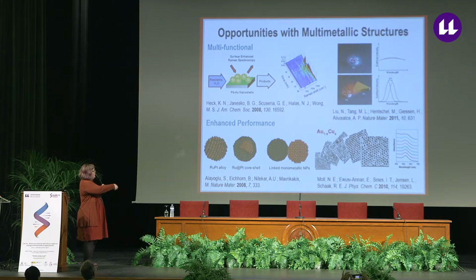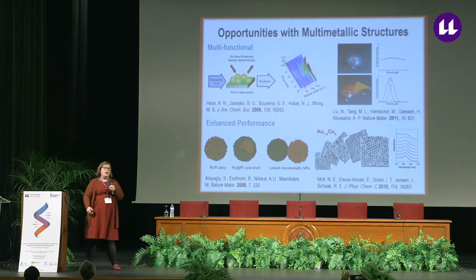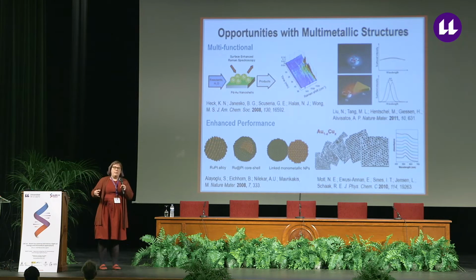The top example is from Naomi Halas and Michael Wong at Rice University, where they had prepared gold nanoshells and decorated the gold nanoshells with palladium islands. The palladium is able to catalyze a hydrodechlorination reaction that they're able to monitor in real time under operating conditions by surface-enhanced Raman spectroscopy that's enabled by the plasmonic gold shells.